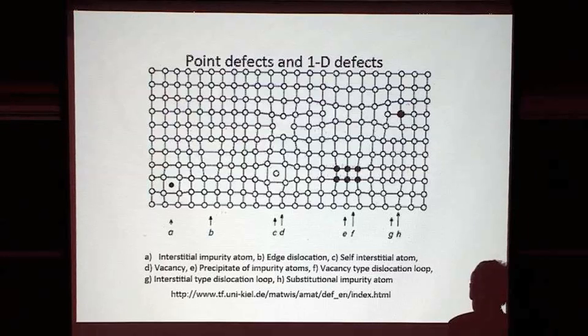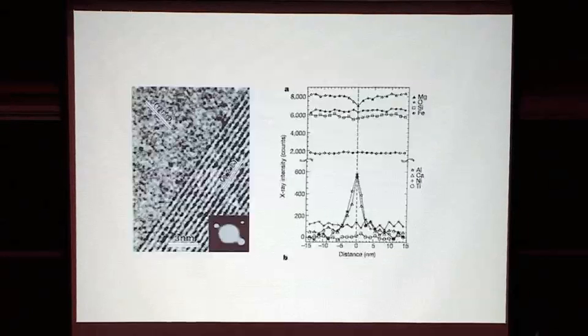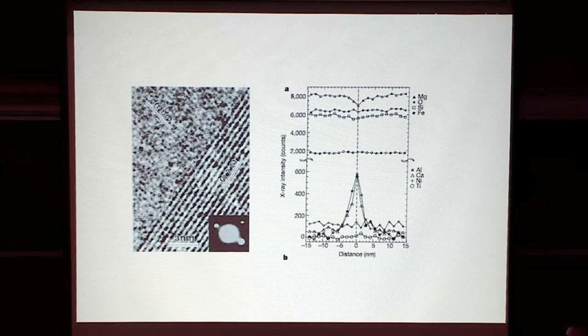And this too, I left out the attribution. This is Hiraga et al. 2004. This is a TEM image of an olivine grain boundary where you can see the lattice fringes of two olivine crystals in different crystallographic orientations. One thing that Takehiko Hiraga was very interested in was that if one looks at the grain boundary, it's an incredibly narrow feature. This is nanometers here, so the feature is just a couple of nanometers across. But he was pointing out that these features are a store of incompatible elements that don't fit in the lattice. So concentrations of aluminum, calcium, things like that in the grain boundary are much, much higher than those found in the background in the olivine.